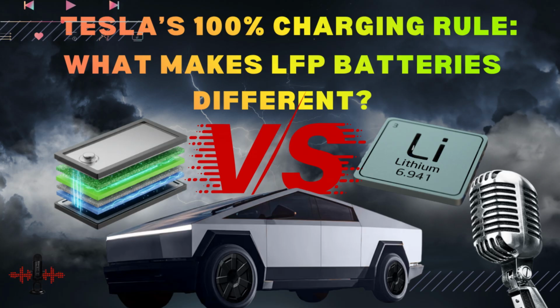And if the structure remains stable? The risk of developing those internal microcracks, the main reason for active material loss in NCM, is virtually eliminated. The structure doesn't move, it doesn't deform, so you dramatically reduce mechanical fatigue over time. This is the breakthrough. When you charge an LFP battery 1,000 times, you are stressing it far, far less than if you charged an NCM battery 1,000 times. You're just running ions in and out of a preset, robust channel, rather than forcing the entire material framework to physically expand and then collapse. And that structural stability is the sole reason we see the 3,000 to 6,000 cycle life scores.